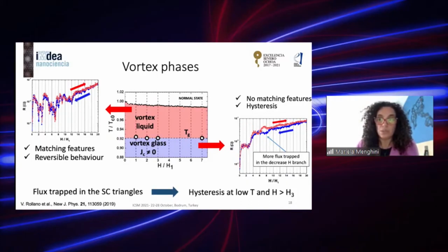While when we go to lower temperatures, to the region where the critical current is different from zero, we see that these matching features are less pronounced, and there is also a hysteresis between going up and going down in magnetic field. And this, again, is consistent with the fact that there can now be flux trapped in the superconducting triangles, so in these niobium triangles, that can cause this hysteresis at low temperatures and larger fields. So this is observed only for fields larger than the third matching field.